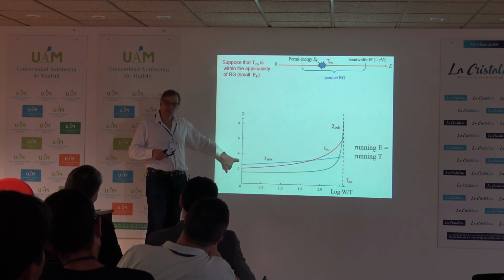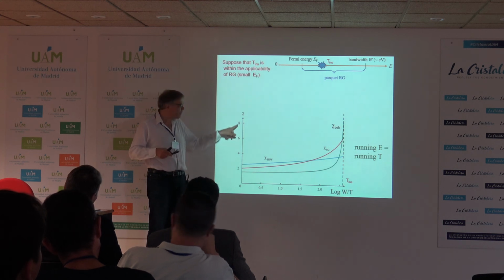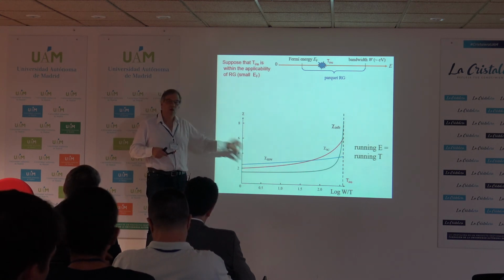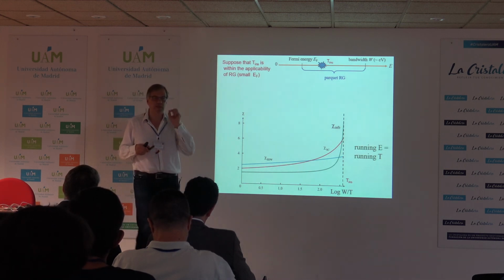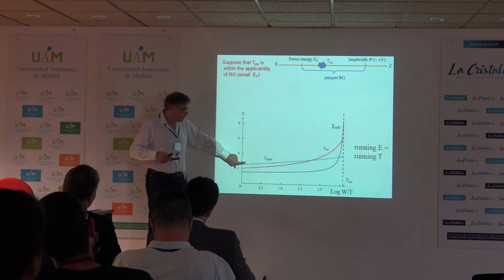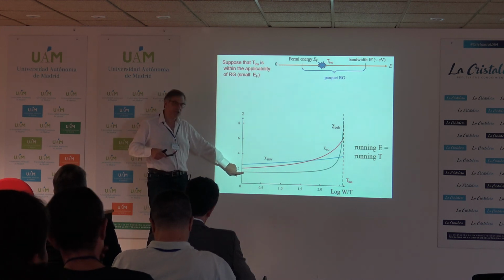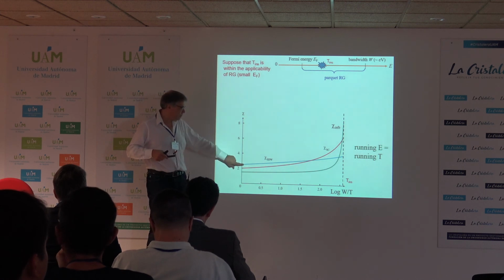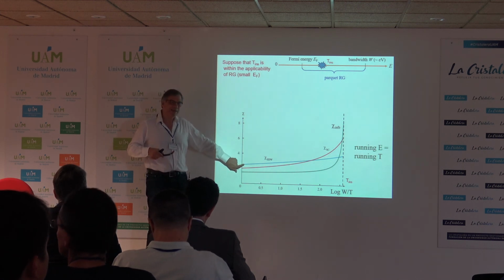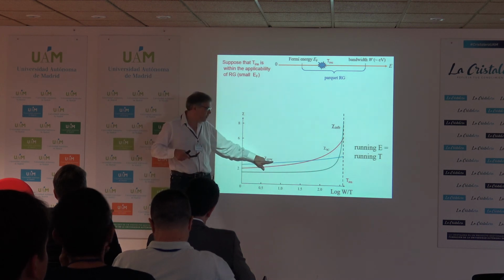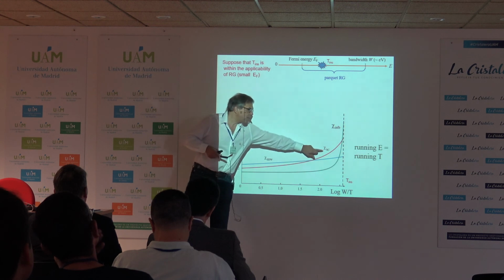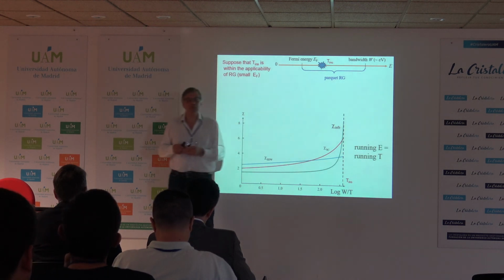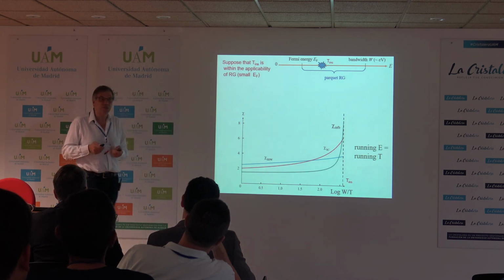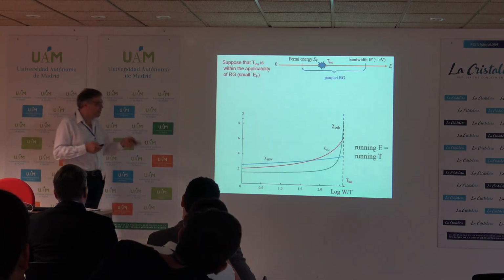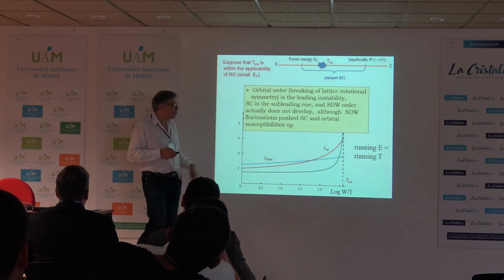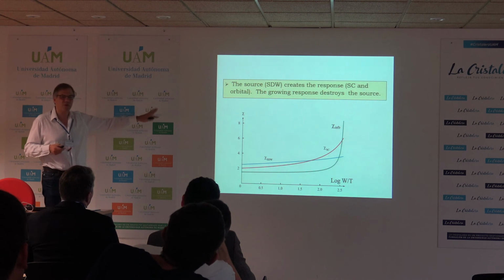Namely, you start with a situation when spin density wave is the largest tendency. What I plot here is susceptibilities in different channels. When susceptibility diverges, it means that the system develops instability. So if I look only here, this is the magnetic channel, this is the superconducting channel, this is the orbital channel. I can make this even larger. So this one is the number one candidate. It runs, and it looks like the system will develop spin density wave. No. At some point, the superconducting channel wins. At the end, the orbital channel wins, which is kind of unusual stuff. And at the end of the day, for this particular case, you develop orbital order, but these are details and this is the important point.